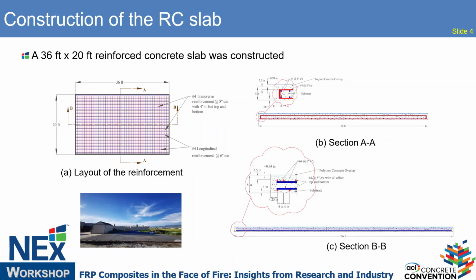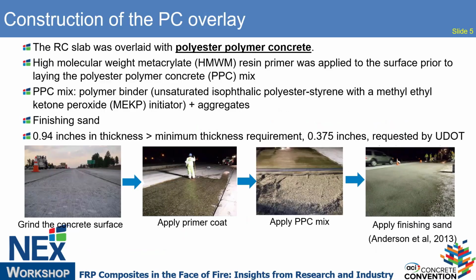So this is a bridge deck. It's a concrete panel. We tried to replicate a bridge deck, and it is 36 feet by 20 feet. And this is the overlay, and the polymer concrete we used is polyester polymer concrete (PPC). Before the construction of the overlay, we graded the concrete surface, and then we applied the primer coating, and then we applied the PPC mix, and after that we applied the finishing sand. And the thickness of the polymer overlay is 0.94 inch on average, which is greater than the minimum thickness required by the Utah Department of Transportation.